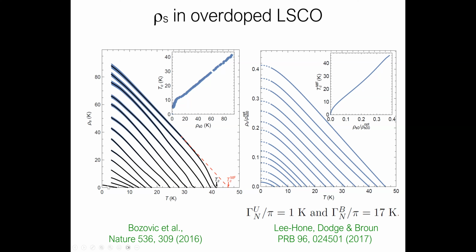So I think it's clear that when TC gets close to the end of the dome, the superfluid density is getting very small in these samples. And so you're going to have phase fluctuations. And therefore, the disorder average theory that I'm presenting is going to break down. Where exactly that happens, I don't have a good feeling for, but I have a feeling that it's about this 10% level of the superfluid density. The same thing that I showed you is related to the inhomogeneity scale.